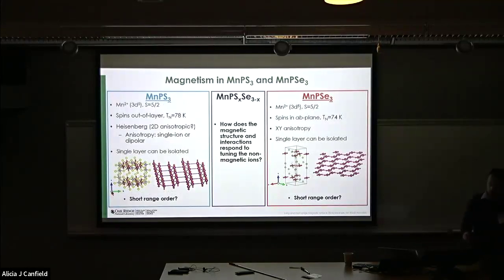Okay, so just a bit of a summary. MnPS3: these are 2+, spin 5/2. These have spins out of the layers with a transition temperature around 78 Kelvin. In MnPSe3, you have the manganese ions on the same hexagonal layers, and the same 2+, normally spin 5/2. Very similar transition temperature, 74 Kelvin. The spins are in the plane.